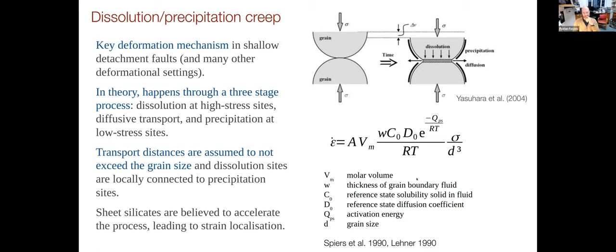In theory, this is a constitutive equation which looks complicated, but it says essentially the rate at which that shortening happens, the strain rate. There's a whole lot of parameters which you don't need to worry about. There's temperature showing up in there. There's a stress exponent, and the grain size. That's an important one. So the stress is over here.